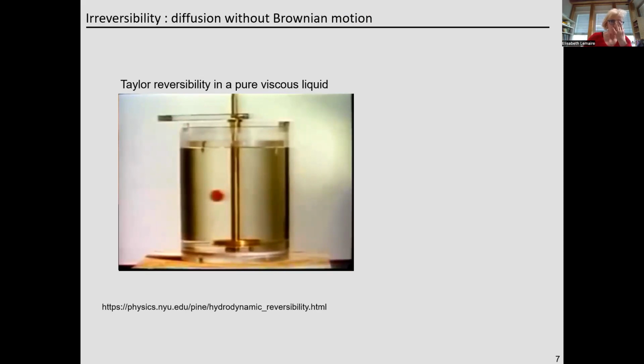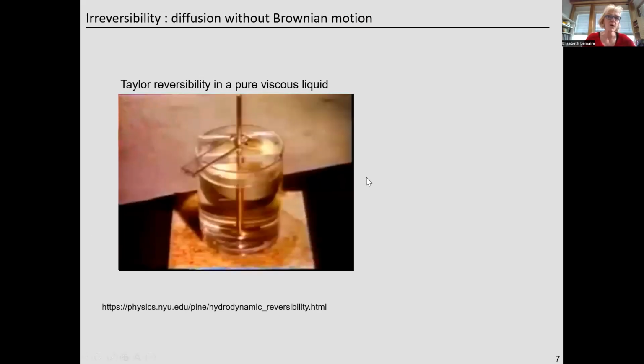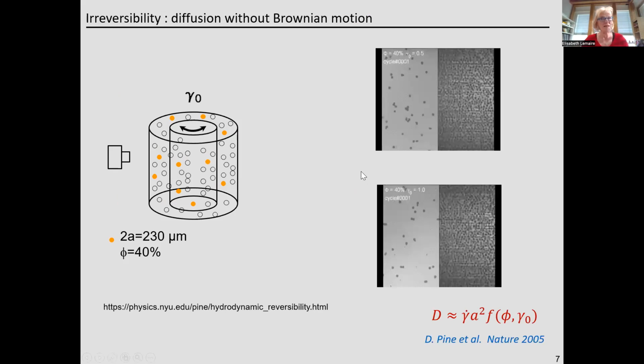So this beautiful experiment, it's a very, very old experiment, but this beautiful experiment shows that at low Reynolds number, flow is reversible. But if you do the same kind of experiment with suspension, you are going to obtain something very, very different. And it is this experiment proposed by Pine. You put concentrated suspension in a Couette cell geometry, and you are going to oscillate the inner cylinder. And you take images of the suspension with a frequency that is the same as the oscillating frequency of the inner cylinder. And then if you do this experiment with a low oscillating amplitude, then you observe almost nothing.